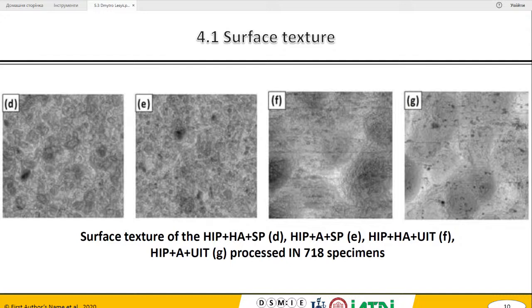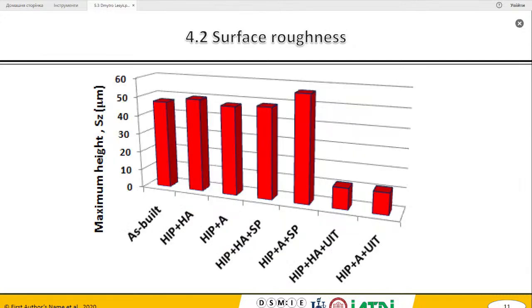Both shot and ultrasonic peening after heat treatments led to a significant change in the shape of the surface profile and form a new wavy microrelief. As compared to the shot peening process, the ultrasonic process on the left side forms regular microrelief with smoother surface roughness and lower surface waviness, owing to application of the multi-pin ultrasonic tool, which produces the sliding impacts of pins by the specimen surface due to forced rotation of the impact head. Next, please. At the same time, the maximum height parameter of the ultrasonic processed specimens was decreased by approximately 4 times in comparison with the heat-treated specimens. Next, please.